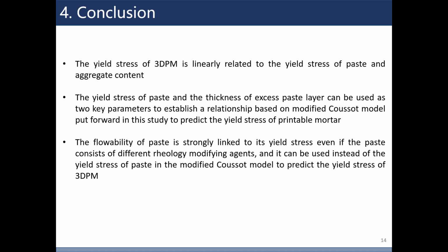The flowability of paste is strongly linked to its yield stress even if the paste consists of different rheological modifying agents, and it can be used instead of the yield stress of paste in the modified Coussot model to predict the yield stress of 3D printing mortar.